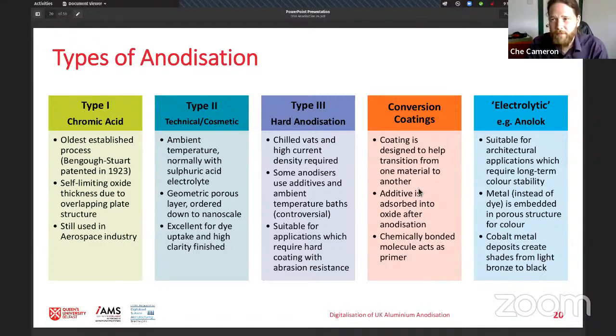We also have type 3 hard anodization, and in this, traditionally, chilled vats down to a cold temperature, between sort of 0 and 10 degrees, are used, and a very high current density. The implication of that is that you need the electrolyte to be cold, and you're putting a lot of energy into it and getting resistive heating, trying to raise that temperature. So the demands upon cooling infrastructure are quite extreme.